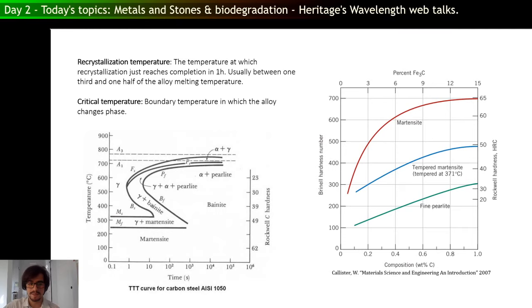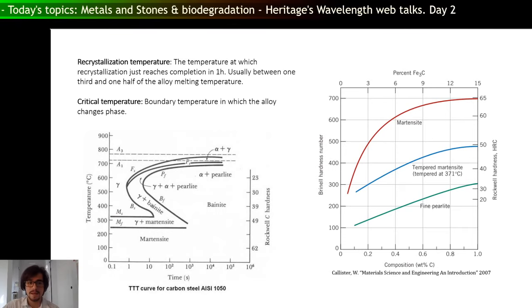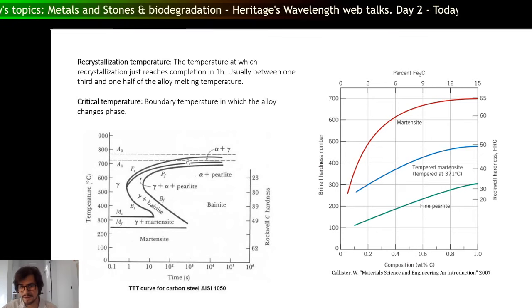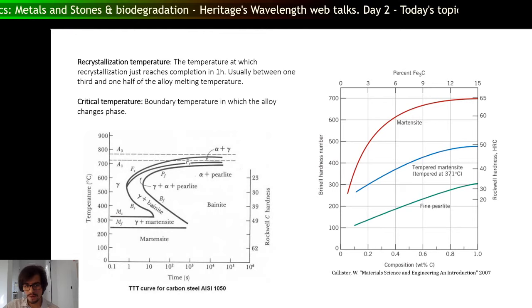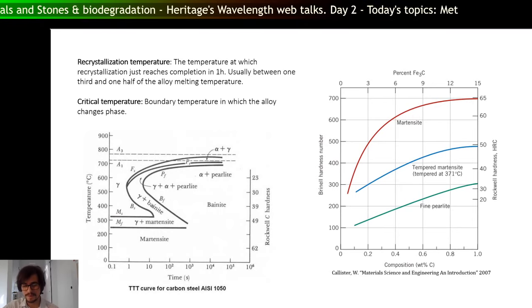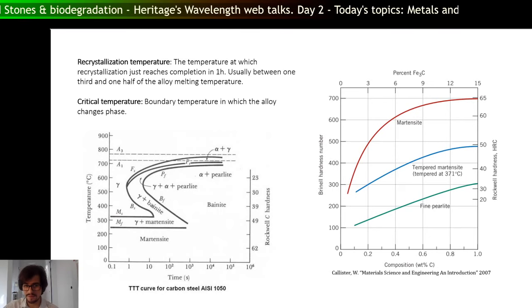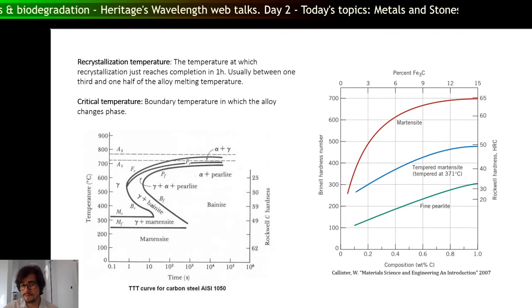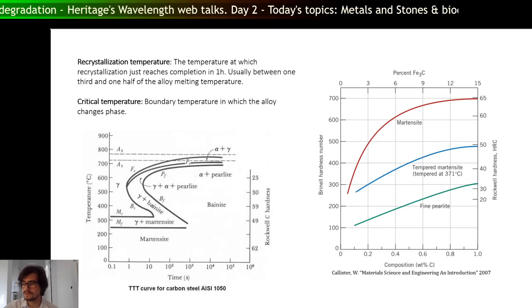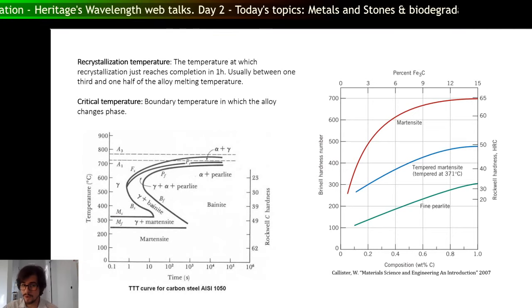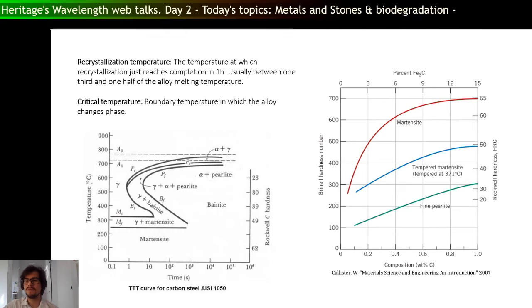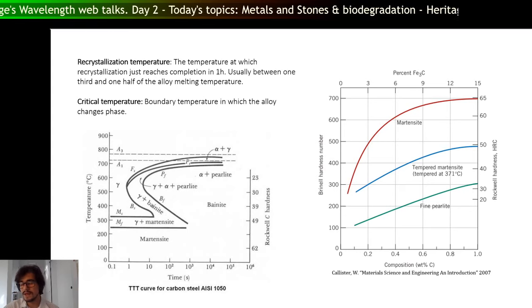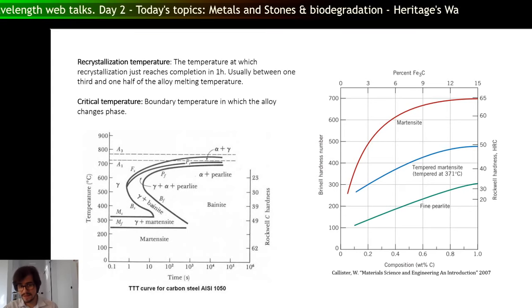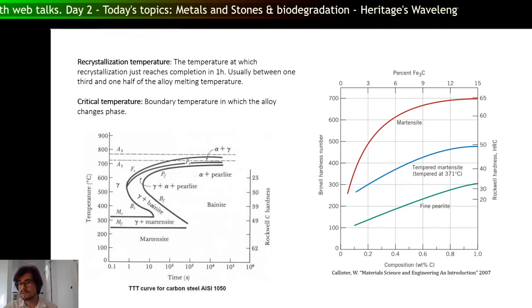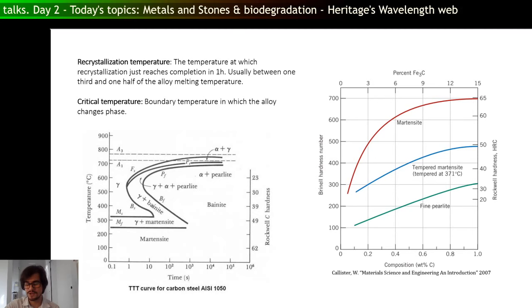And you can look at this TTT curve or a CCT curve. It has different phases, and temperature and time here. And then you have hardness. So the faster you cool it, the harder the material you will have, the harder phase you will have, but it is also brittle. Remember, you are introducing a lot of defects in your material if you are cooling it too fast. Then you can reheat it once again to relieve a little bit of stress and make the crystal grains larger so you have fewer defects. So you are relieving a little bit of the stress. So you have a more ductile piece with a martensite structure as well. So this is a very good steel.